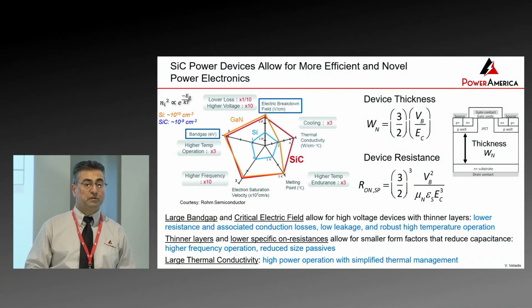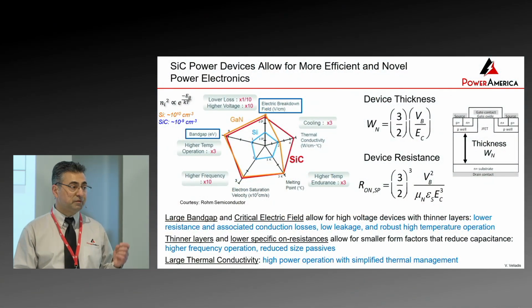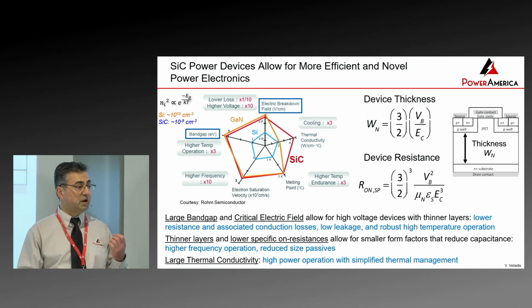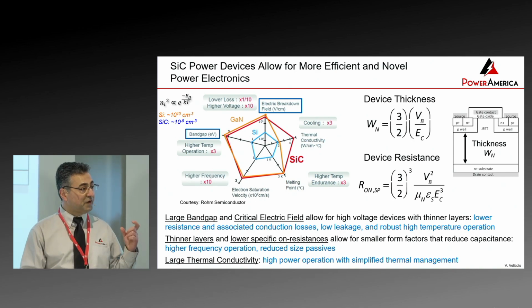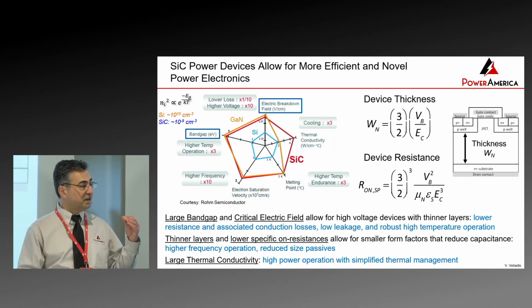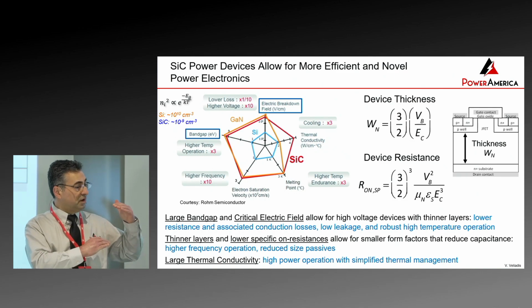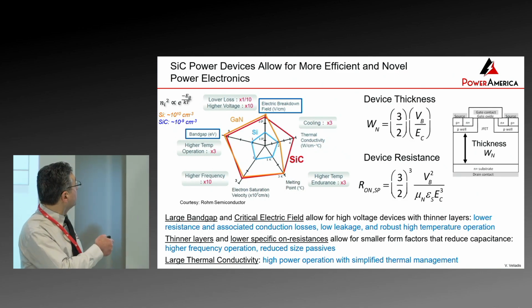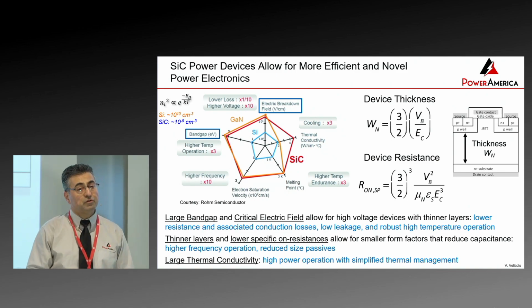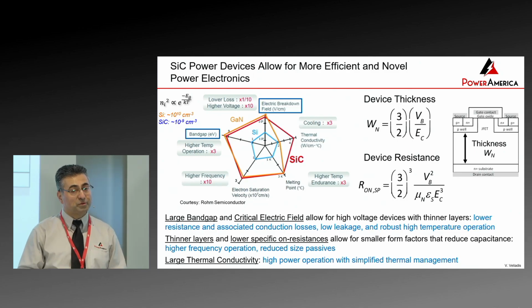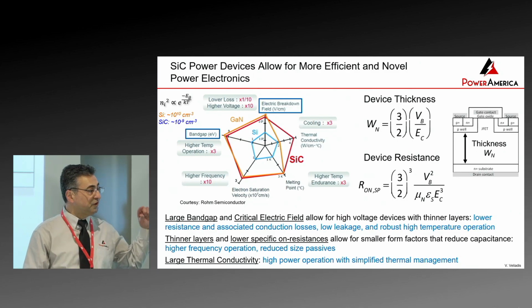The fact that we have a large band gap and a very high critical electric field means we can make silicon carbide and GaN devices with thinner layers. So thinner layers means low resistance, lower conduction losses. And of course, the fact that you have a wide band gap means that your leakage is lower because thermally excited carriers now have a bigger band gap to go through. And you can see that from this equation here, which is for room temperature. And of course, thinner layers and lower specific on resistance means that the device will be smaller, capacitance will be smaller, you can operate at higher frequency.